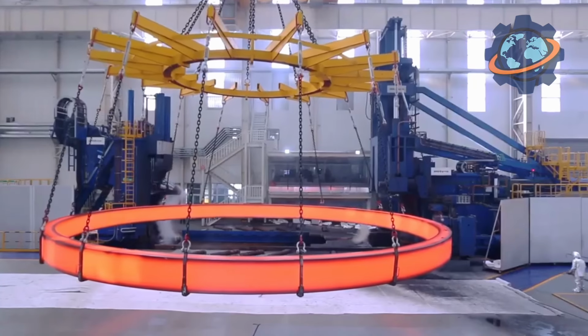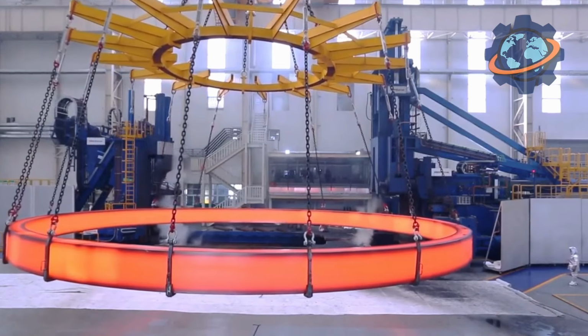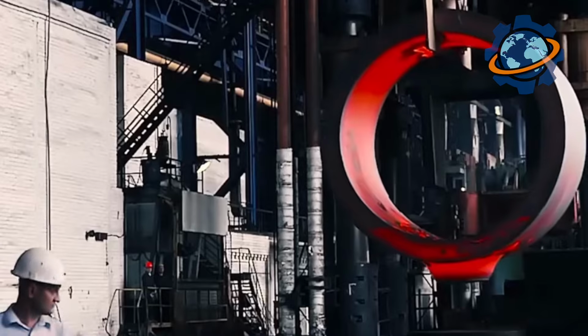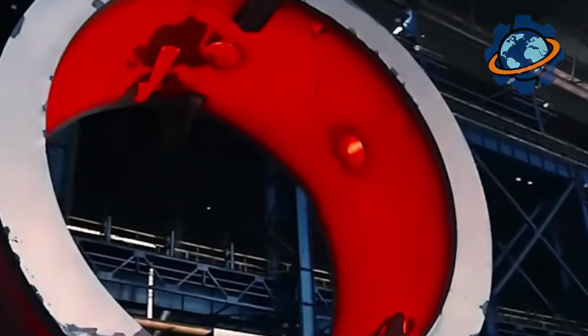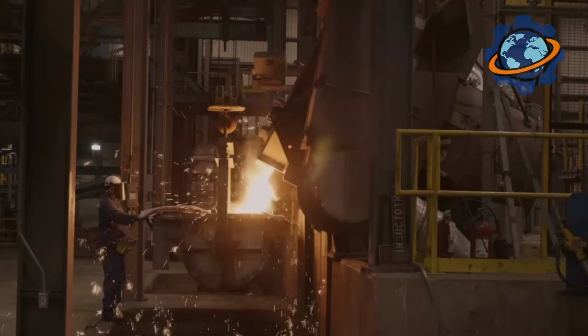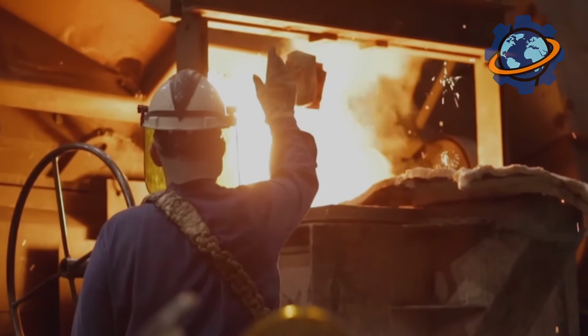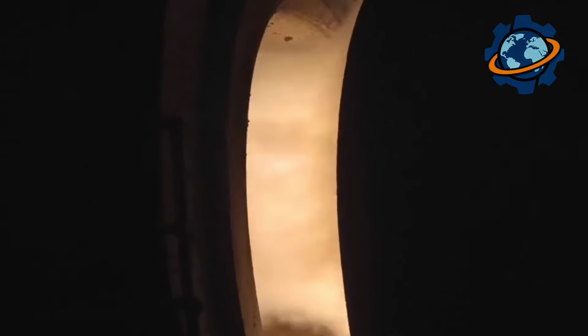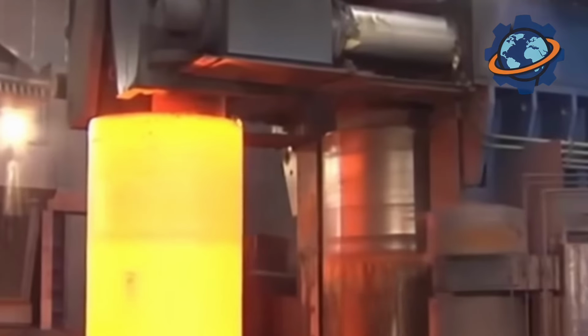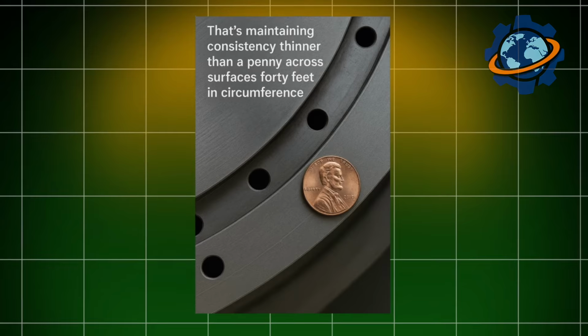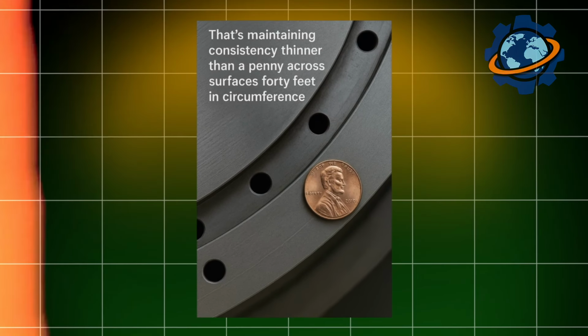The forged cylinder, now weighing 450 tons after material redistribution, moves to vertical lathes with cutting surfaces 20 feet in diameter. Carbide tools, costing thousands of dollars and lasting mere hours, remove steel in continuous spiral cuts. Metal shavings, glowing red from friction heat, pile like metallic spaghetti. Picture this. Machinists target wall thickness of 8.7 inches with tolerance of plus or minus 0.05 inches. That's maintaining consistency thinner than a penny across surfaces 40 feet in circumference.